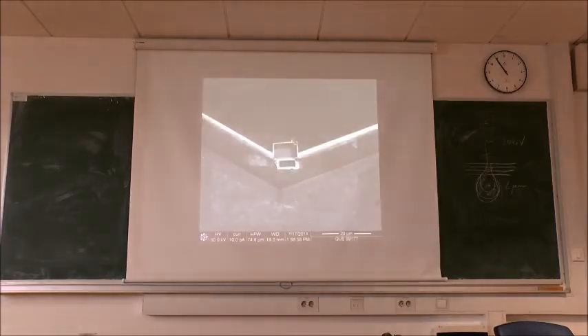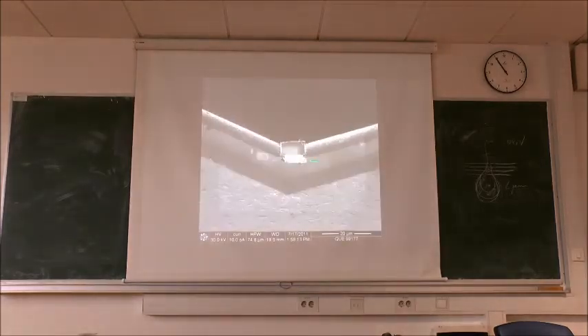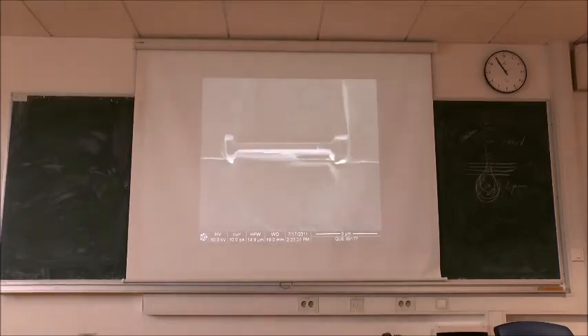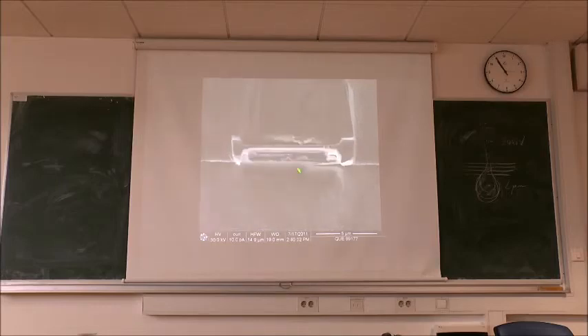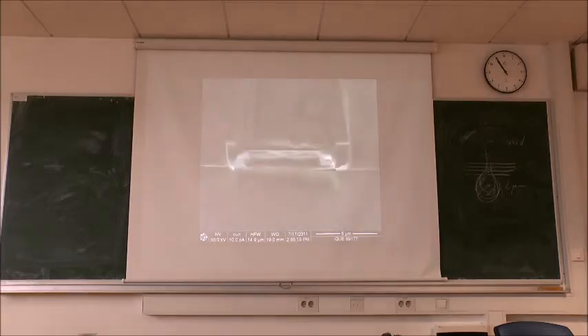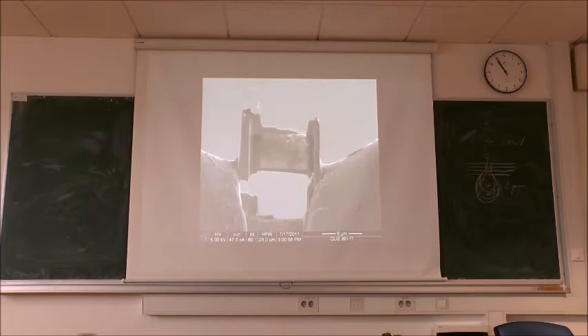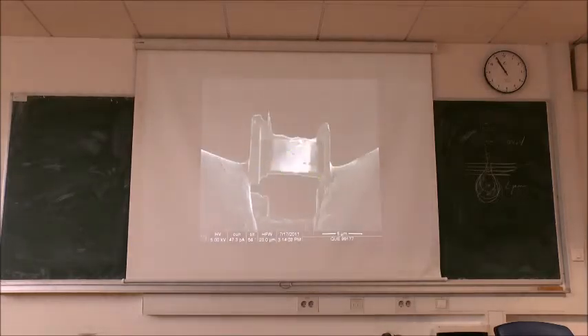Okay, maybe the final or semi-final act, now you have to really do fine thinning of your lamella. Still, I would say it's maybe something like 2 microns, definitely too thick. But if you can go down to 50, 70 nanometers, maybe like this one here, and especially again using low energy, so that you will not end up with an amorphous lamella. At the end, you see here, some areas are really, really thin. And that's it, the happy end.